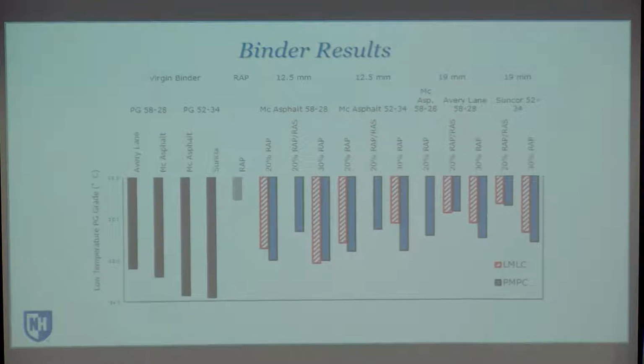In terms of the wrap, you can see New England, we don't have super stiff RAP, so if you noticed on the high side it was an 82. On the low side, I think it was around a minus 18. But if you look at the response of the mixtures, again, we're seeing similar kinds of things that we saw on the high side, in terms of the changes with the different recycled material type and content, and also the differences between the laboratory and the plant.